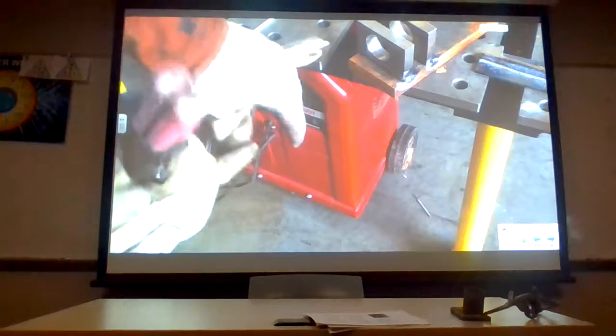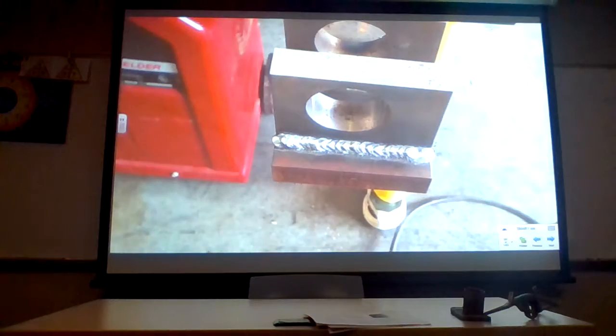I want to kind of figure out the best way to put the rod in the clamp here, the electrode holder. Remember what I told you, technically it's referred to as an electrode, not a rod, because it does conduct current. Again, the 6011 is doing a really slight whip and pause and forward and back motion. A lot of people use a lot more of a whip to come out of the puddle a little bit further than that. But I actually want to build up a little bit of a crown or fill on a weld like this, so I'm just making a short movement.